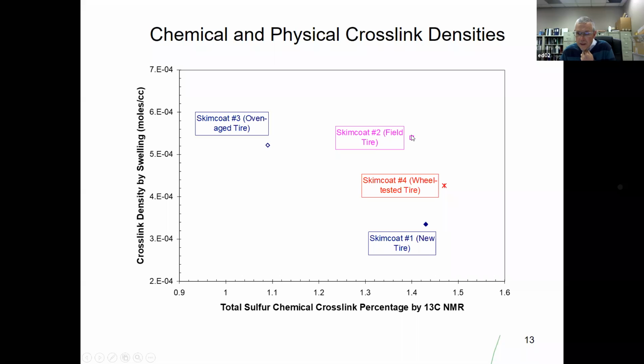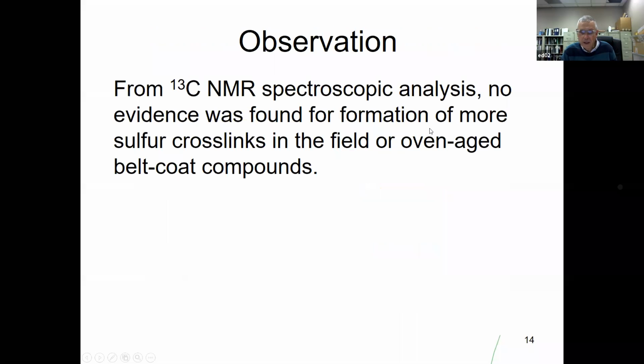It shows clearly that the field tire and the oven aged tire are not increasing the percent of carbons that are bonded to a sulfur. So from this data, we say there is no way that you're driving down the road and continuing vulcanization in your tire. From carbon-13 spectroscopic analysis, no evidence was found for formation of more sulfur crosslinks in the field or the oven aged belt coat compounds.